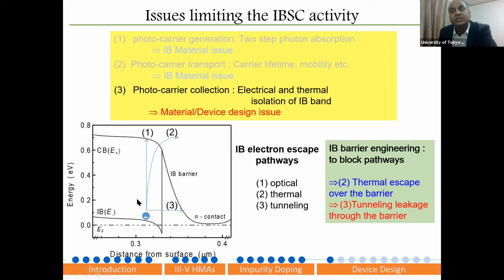For an intermediate band gap, it is very, very vital. You get the current, but you should not compromise the voltage. For the voltage, you need a second photon coming from here to excite the electron in step 1. This is what we love, but we don't want to see step 3 or step 2, where the electron goes out. You can get current, but you will not get the voltage. So for the intermediate band, two processes are very important: you have to have a good intermediate band barrier, and you must make sure the electron in your intermediate band does not escape by thermal heating or by tunneling. So you should design a good intermediate band barrier.